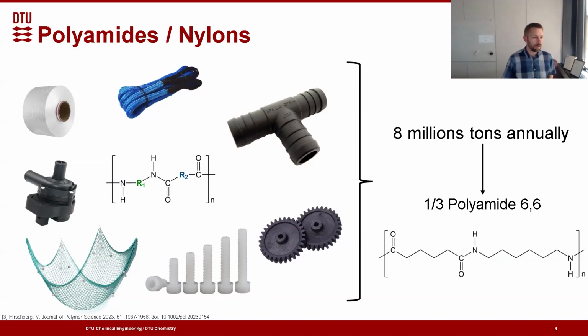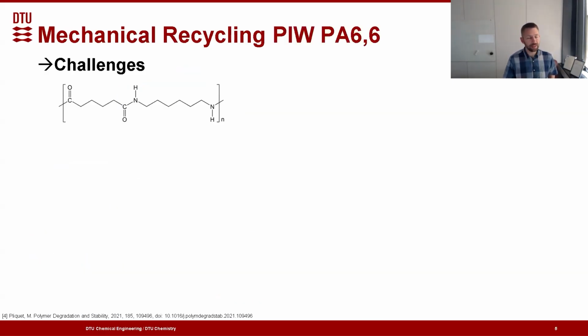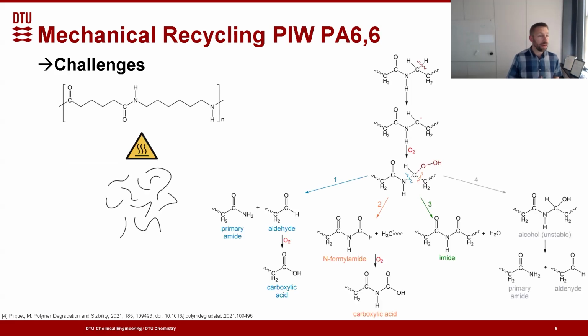The polyamide structure, as you can see in the slide, is built around an amide structure with different types of spacers. But for polyamide 6,6, that is a carbon spacer from a dicarboxylic acid and a diamine. That also means that we have heterofunctional atoms in the backbone. This may sound a bit complicated, but it is actually rather important, because that means that once we start heating these polymers in processing, a broad range of degradation phenomena will take place. These can be of more or of less importance to the recycling of these polymers.